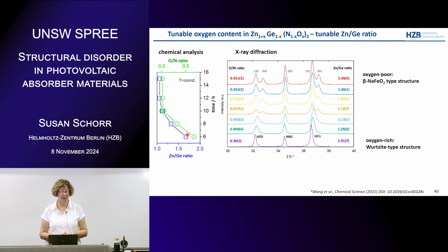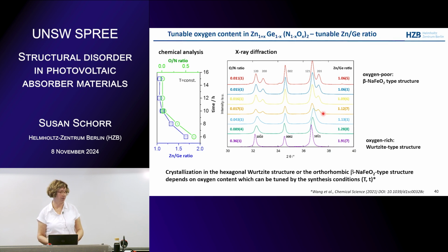And we could already see from this XRD pattern that the oxygen-rich compounds crystallize in the wurtzite type and the oxygen-poor in the beta sodium ferrite type structure. Why do we see this? Well, you see here this peak splitting. So this peak here splits into two peaks. This stays as one peak, and this splits also into two. This is an indication of a changing crystal structure. And in principle, it depends on the synthesis conditions, the temperature and the reaction time.